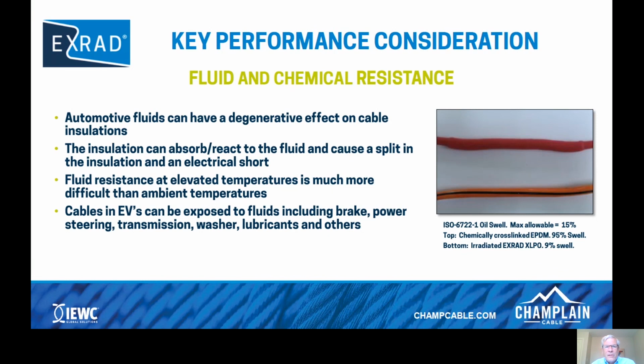Fluid and chemical resistance. Automotive fluids can have a degenerative effect on cable insulations. The insulation can absorb and react to the fluid, causing a split in the insulation and resulting in an electrical short. When the insulation absorbs, say, an oil and swells, it becomes softer and much less tough. Its tensile strength is often cut in half or even cut down to 25%.